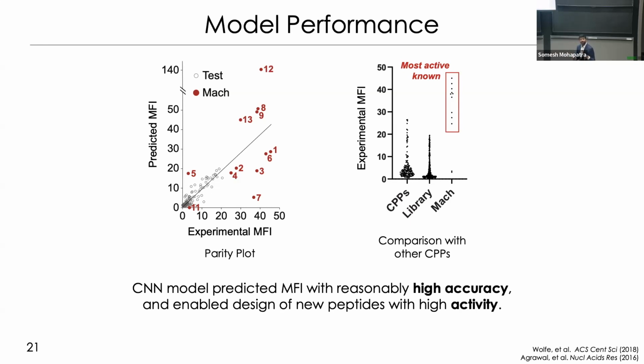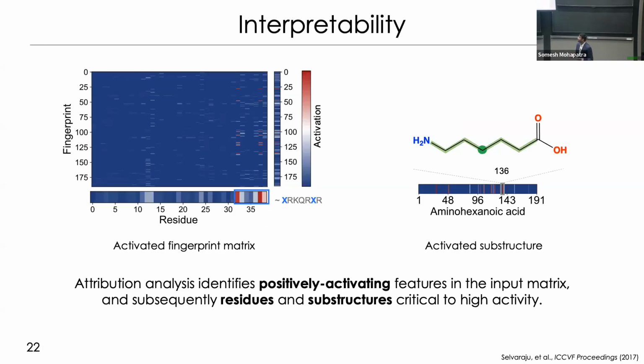And what was most critical in this part was the framework was able to discover peptides that were most active amongst all cell penetrating peptides known at that point. The library had a maximum of around 20, and some of the peptides that we saw in the literature were around 30. And we got many peptides that were 50-fold active in helping deliver this oligonucleotide therapeutic. And at this point, we were pretty curious as to what the model is seeing in these peptides that makes it make such decisions. That curiosity led us to look at this from an attribution analysis perspective, to interpret the decision-making process of the model. So looking at this input feature matrix, we looked at all those features that triggered the model to make such a prediction.